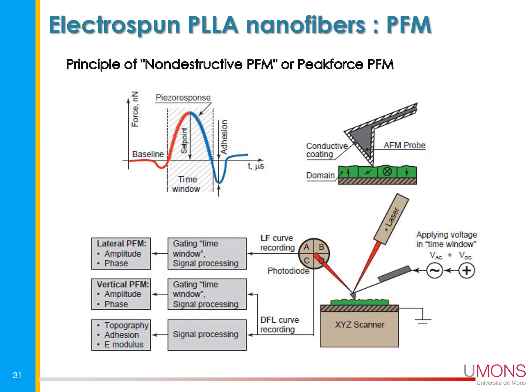So as promised before, and I will finish with that, the idea, because in most of the techniques that we use, PFM, we are in contact and the force is quite large. The idea is to combine the piezo measurement with the peak force tapping, because in peak force tapping you can control the force that you apply to your sample. And during this time window, when the tip is in contact with the sample, you can start to play with the piezo itself, and you apply, as we saw before, the AC and the DC, and we measure